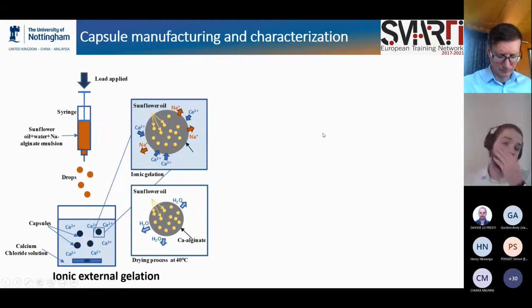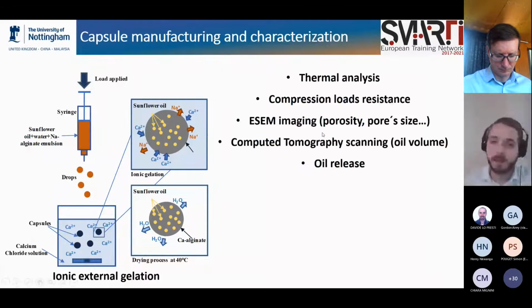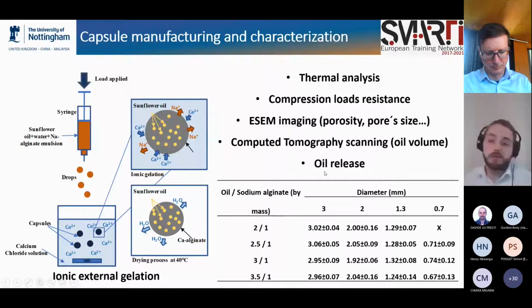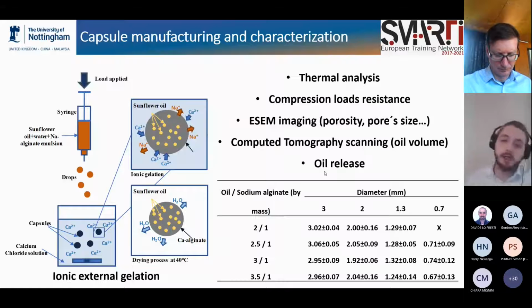As a methodology, it's important to explain the process of the capsule manufacturing. It was based on ionic gelation. So basically, we produced an emulsion based on sunflower oil, water, and sodium alginate, and we dropped it in a calcium chloride solution where the chemical reaction takes place, an ion exchange. And because of this ion exchange, we create the capsule, and the sunflower oil is encapsulated inside of a shell. Basically, we produced different types of capsules, modifying the diameter of the capsule and also the strength, just by modifying the amounts of sunflower oil or sodium alginate during the emulsion production.